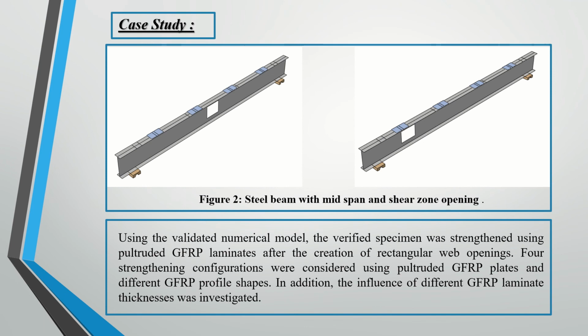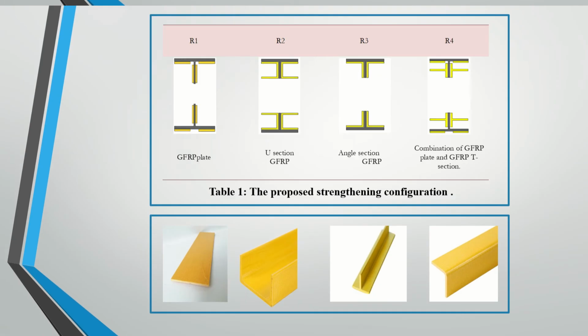Using the validated numerical model, the verified specimen was strengthened using pultruded GFRP laminates. Four strengthening configurations were considered using pultruded GFRP plates and different GFRP profile shapes. In addition, the influence of different GFRP laminate thicknesses was investigated.